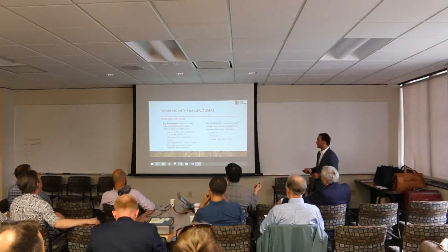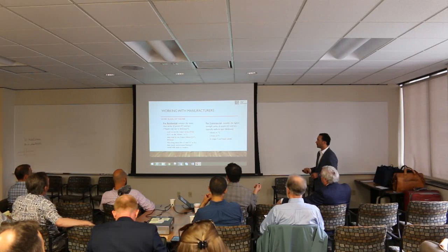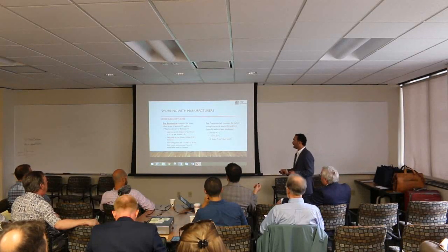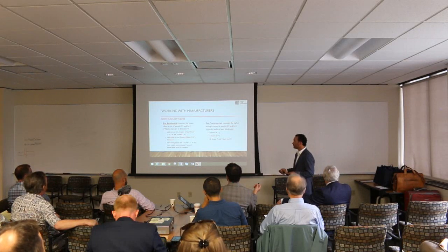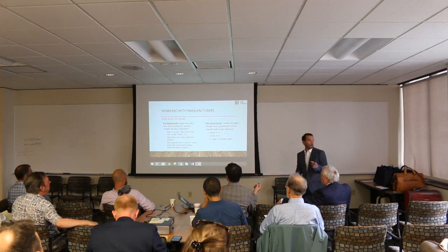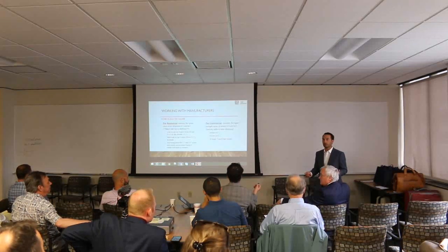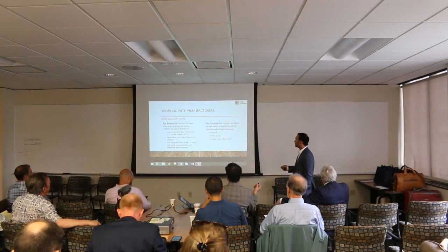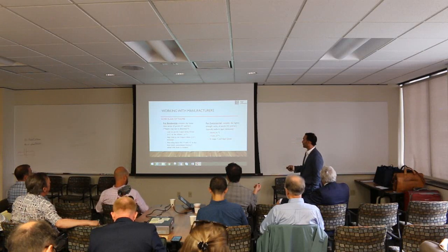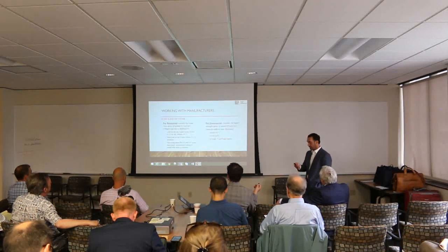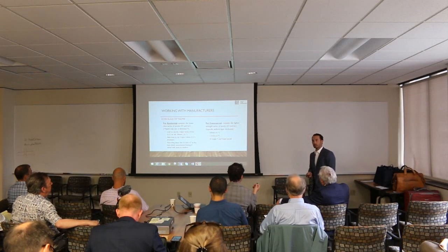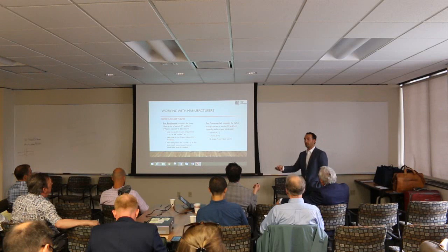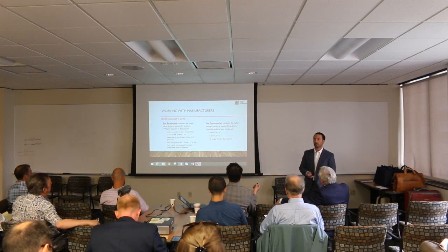What you might be looking for on the residential stuff, a 3-layer series, 87 millimeter, a 3.5. A 5-layer series, which is somewhere around the 139 millimeter, meets 5.5. The nice thing about those is that you're meeting up with your conventional dimensioning if you're mixing that with dimensional lumber. If you're doing commercial, whether it's a 3, 5, 7, or 9 layer, you're looking at these kind of dimensions, 4.1, 6.9. So little oddball numbers on the thicknesses there. But again, talk with your manufacturers. Everybody's slightly different. A 5-layer panel by one manufacturer is not the exact same dimensions as the next manufacturer.